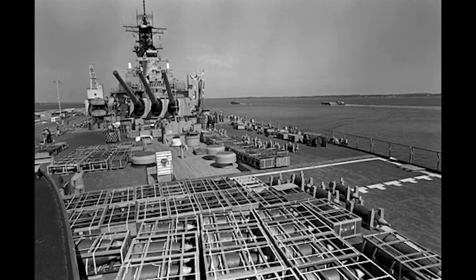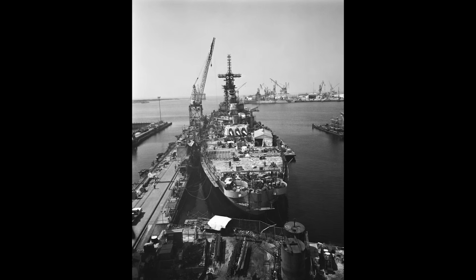The face would crack, and the cracks would propagate through the brittle material faster than the back layer could absorb the impact energy. Large sections would spall off. The projectile fragments would penetrate through material that had lost its structural integrity. The Navy had discovered a fundamental principle of armor design. Optimization for one threat could create vulnerability to a different threat. The MNC armor was optimized to shatter projectiles, and it succeeded brilliantly at that task against smaller projectiles. But against larger projectiles, carrying far more kinetic energy, the very characteristics that made the armor effective at shattering shells, the thick, brittle face, became the mechanism of catastrophic failure.